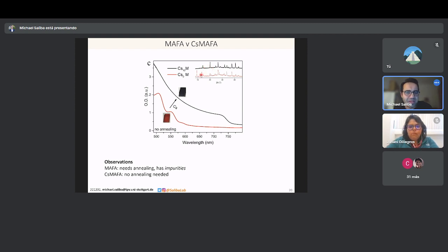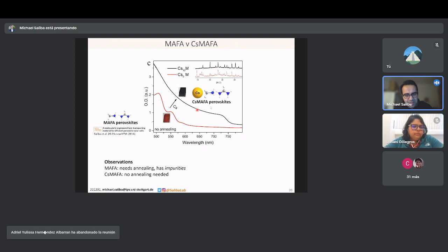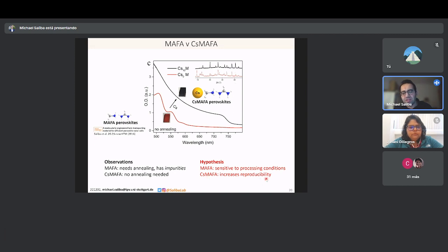Of course, we still have a lot of solvent in here, but it was very clear that this is a completely different film formation before the annealing is started. So that's what you see here, these triple cations. And the hypothesis was that MAFA-based perovskites are much more sensitive compared to the triple cations, which increase the reproducibility by being insensitive, so to speak, to the environmental conditions.